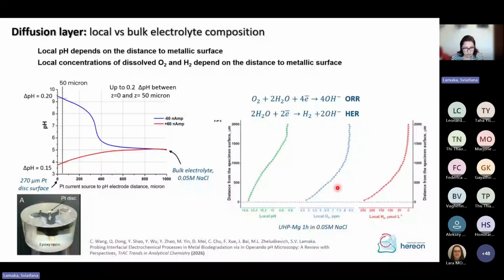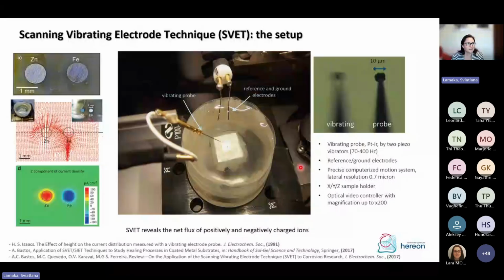All right, now let's move to the techniques. We start with SVET. Basically, SVET reveals net fluxes of positively and negatively charged ions. I took this very nice image from publications of Dr. Alexandre Bastos from the University of Aveiro. He is probably the strongest expert in SVET methods and has published very valuable, very informative reviews on this topic. In this work, he galvanically connected zinc and iron electrodes embedded in epoxy, so there is galvanic corrosion going on. With SVET, it's very easy to visualize this upward flux of charged zinc ions and also the flux of negatively charged OH ions due to the cathodic process on iron, which is why it looks like a downward flux. And basically, this is what SVET is doing, measuring the net fluxes of positively and negatively charged ions.